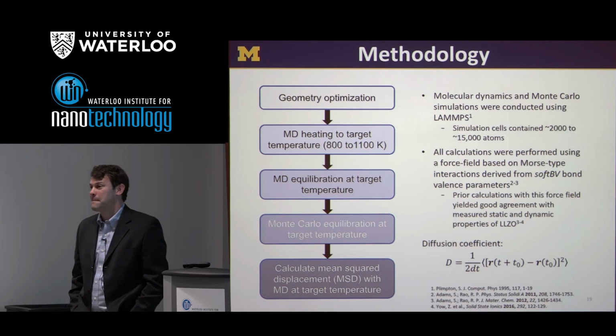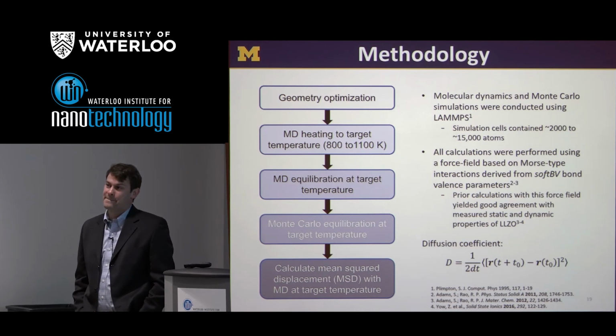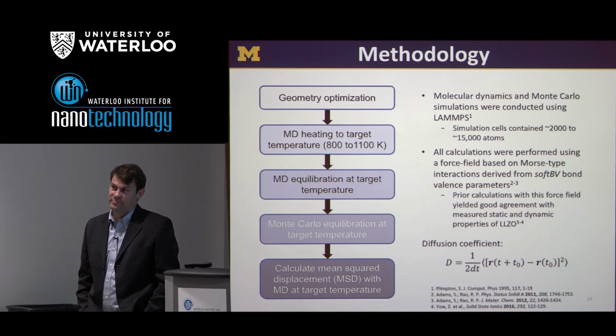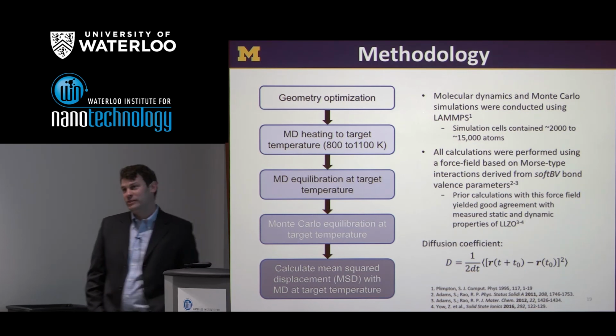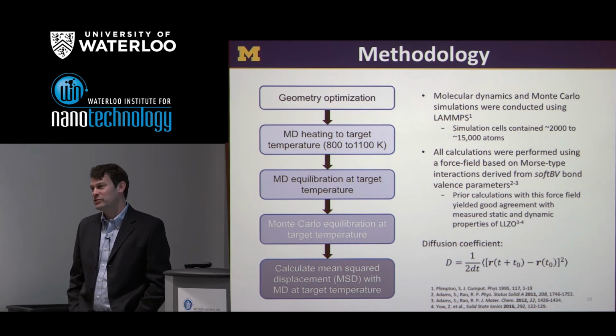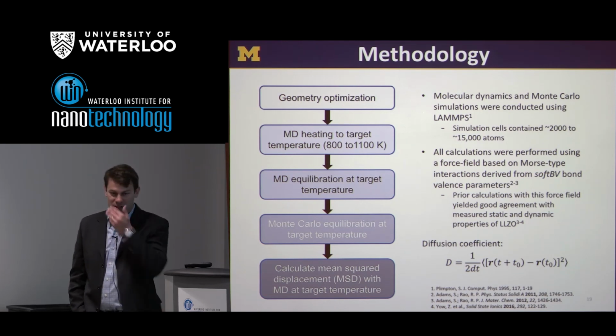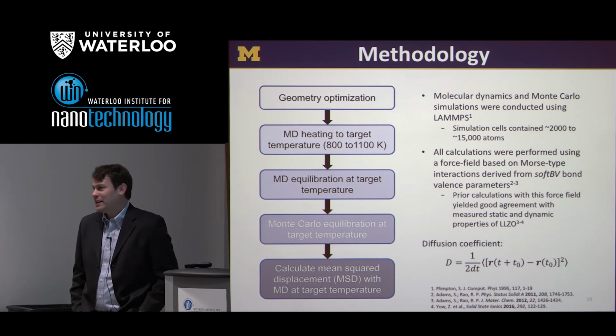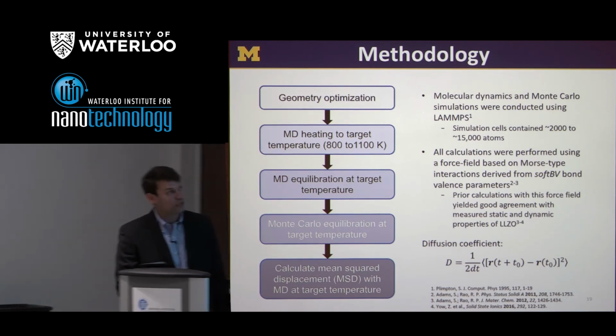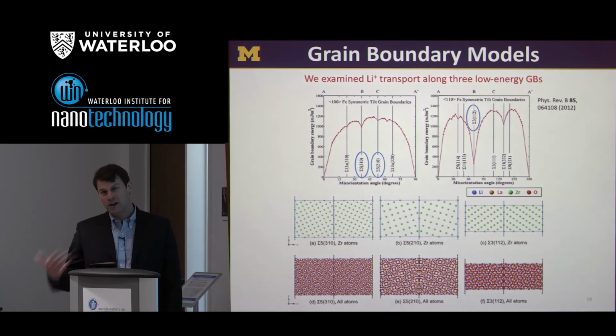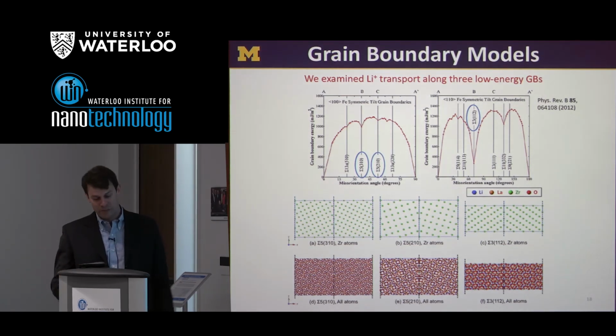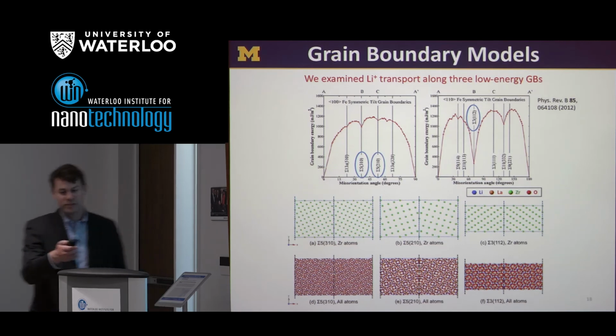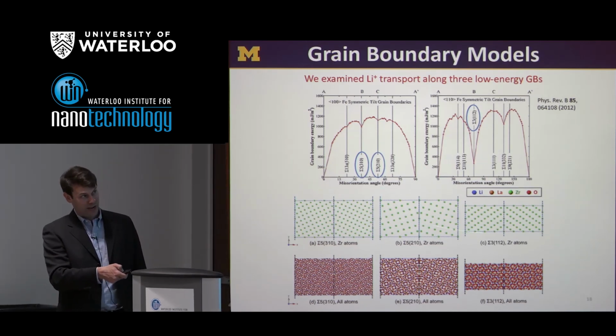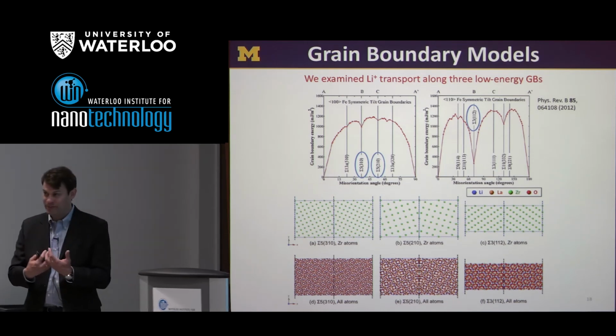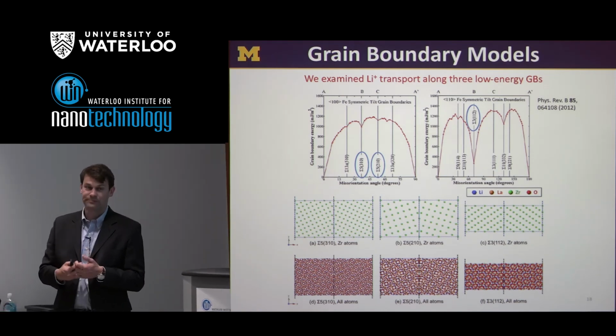Second question about the grain boundary connectivity. What are the general ways to improve the grain boundary connectivity? I think you could of course just anneal the system at higher temperatures, and presumably if you had some disorder, maybe dislocations at the grain boundaries, those would anneal out. One could expect that if you heat the system for a long enough period of time at a high enough temperature without melting it, you would come rather close to achieving grain boundaries that looked like these nice compact coincident site boundaries that I have here.